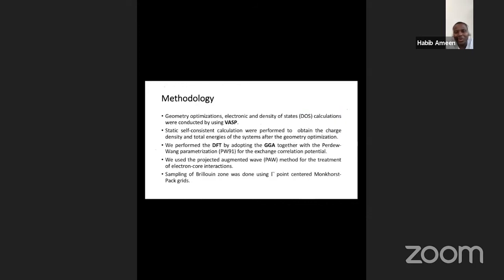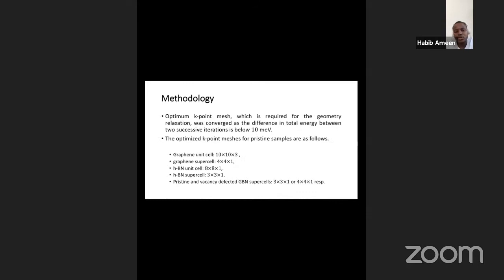Okay, so the methodology. The software that we use is VASP, the Vienna Ab initio Simulation Package. It's a popular software used by computational material scientists and computational physicists for running density functional theory calculations. We perform DFT by adopting the GGA together with PW91 for the exchange correlation potentials. Okay. Also, for the k-point sampling, this is all the process that we follow for the hBN. These are the dimensions, 8 by 8 by 1. All the details are explained here.